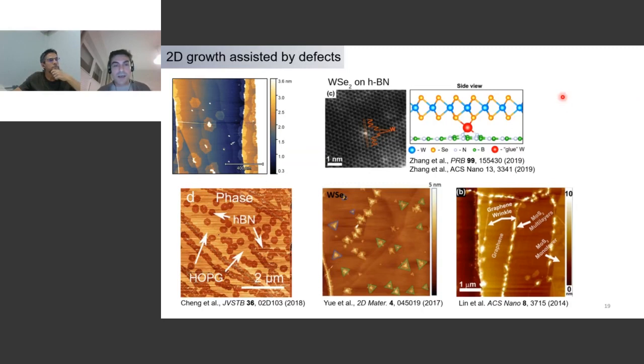There's also a group showing that when you grow TMDC on HBN, very similar things happen, and they have some calculations that support that you do have this defect-assisted van der Waals growth, if you will. So this seems to be a general effect. But of course, the problem here is that if this nucleation is so disordered, then you would expect that this will influence the growth.